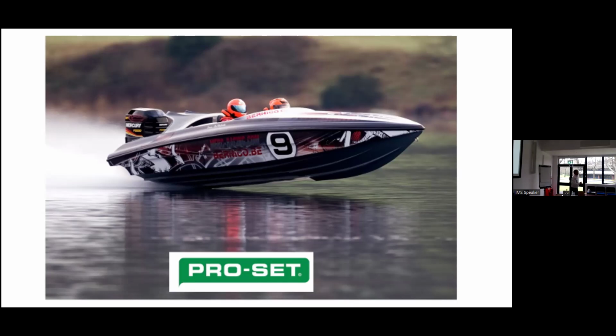You can have light and fit for purpose, but you can't get down to the weights that you're looking for here. These are laminate thicknesses on this boat. It held the Windermere speed record for that class of outboard. I think it was 100 and something insane, 108 miles an hour. And you can see it's barely a boat. It's partially riding on a cushion of air. Pretty insane. The laminates on that are not much thicker than a good quality photocopy paper either side of foam core. So very light, but actually very durable as well.